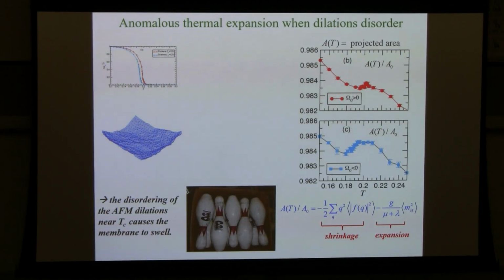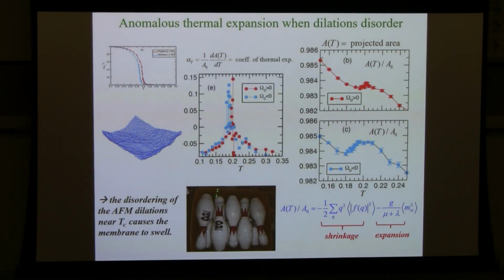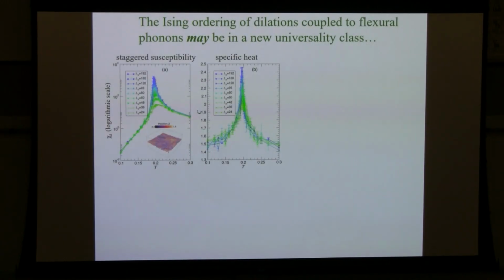And so you can tune, by going close to this phase transition, the coefficient of thermal expansion, which is just the slope, to be 0. And here are the two contributions that we find in a simple kind of renormalization group enhanced Landau theory. And here is the actual coefficient of thermal expansion, the derivative of these curves. It is a little bit noisy, but you can see it goes through 0. There are other materials where you can do this, like water above the freezing point. You can get the coefficient of thermal expansion to vanish. Here we can also get it to vanish.